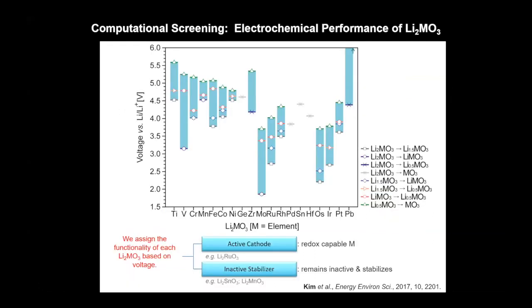Other things we can look at to screen materials like this is the electrochemical performance. So we can start removing lithium from these compounds and calculating the energy costs to remove lithium, or in other words, the voltage associated with these materials. And these are just voltages. This plot is just voltages of given materials for various amounts of delithiation, if you will.